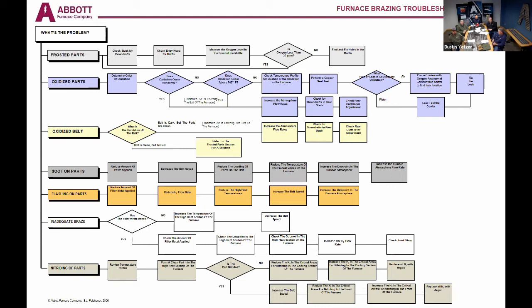So we see frosted parts or oxidized parts. Most of that comes from downdrafts in the stack, some of the things the guys were talking about, seasonal change, those kinds of things. Frosting usually happens in the front of the furnace, and oxidation is usually in the rear of the furnace. Soot on parts. If you have contamination, it kind of depends on whether you're using a paste to make the braze joint or a preform. Some of those have binders in them, so it can be the amount of paste that's being applied. It can also be related to the belt speed on how those binders and what temperature those binders are coming out at. One of the most common things we see is flashing on parts.